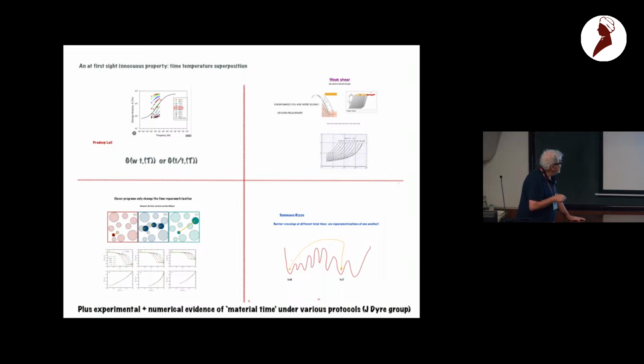Something that we recently did, and now the authors are invisible, but there is Ludovic here, is to look at the programs that Ludovic and co-workers had developed for super-accelerating the dynamics of glasses. And we tried to check if it was an instance of the same film, but just that, thanks to Ludovic's magic, was passed faster. If you didn't know the theory, you would have no reason to believe that was going to be the case, but it is.